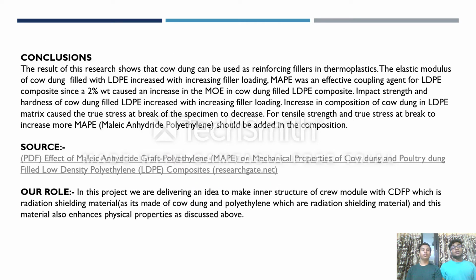Now, conclusion. The conclusion of this research shows that cow dung can be used as a reinforcing filler in thermoplastic. So, the elastic modulus of cow dung filled LDPE, which is low density polyethylene, increased with increasing filler loading. MAPE, maleic anhydride polyethylene, was an effective coupling agent for LDPE composite, since a 2% weight caused an increase in the modulus of elasticity in cow dung filled LDPE composite.